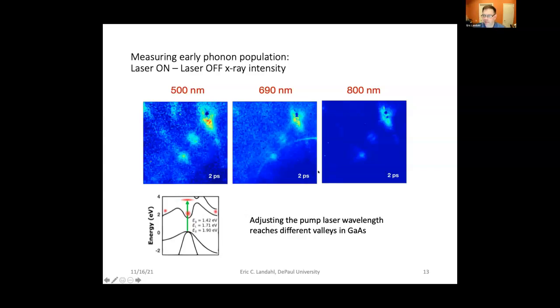Where it starts to not make sense, and I didn't show this data, is that the dynamics are also very different subsequently for these longer wavelengths, where we're not as efficiently filling all of the valleys, and that we can't explain yet. The other data I showed on gallium arsenide was all taken at 500 nanometers, much higher than the gap. Okay.